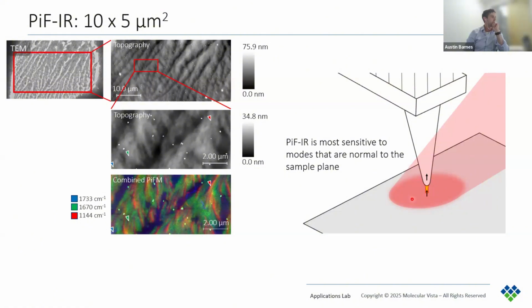One question is about the amplitude of the photo-induced, the PiFM channel itself, not the topography. Typically, you said the amplitude of the second eigenmode is about 1 to 2 nanometers. That's what we use for topography tracking. Then what we're actually recording is the photo-induced force response, which is based off the amplitude at its fundamental frequency, typically due to the dipole moment that is induced into the material. There could be other forces at play, but what are the typical amplitudes in that PiFM channel that the cantilever is typically seeing?